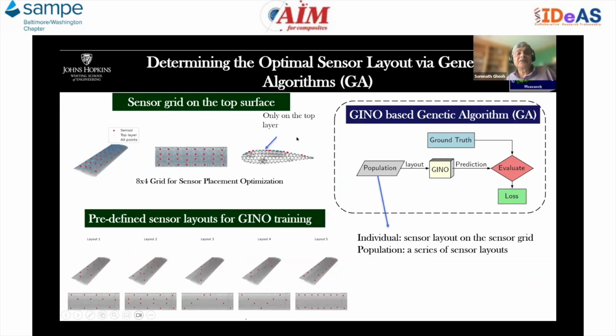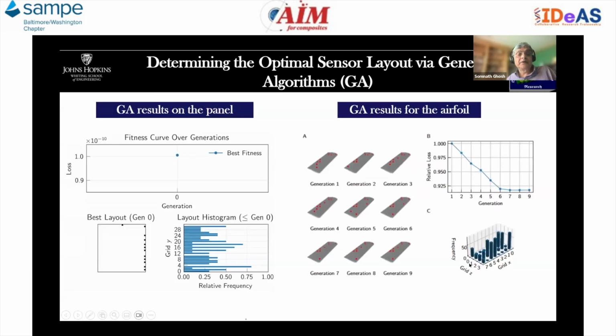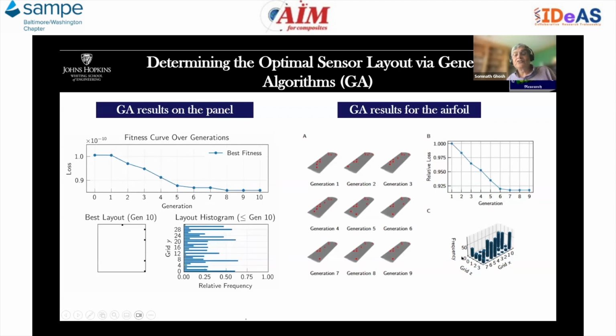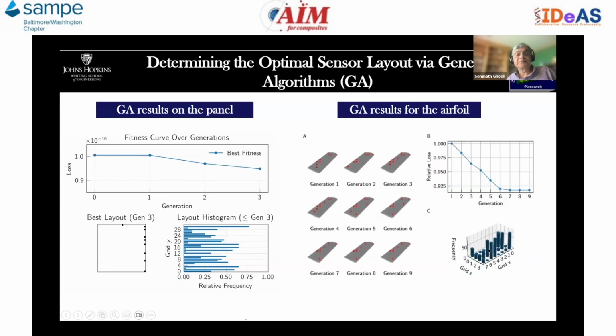The last thing here is we also have coupled this analysis with a genetic algorithm-based optimal sensor layout schema, where you can train this genetic algorithm using basically the placement. This is a sensor grid on the top surface, and these are some of the sensor layouts, and you can basically use this GA to come up with a loss function that corresponds to the difference between the ground truth and the predicted values corresponding to different sensor layouts to give the optimal behavior. So these are some of the sensor layouts for the panel, and this corresponds to some of the sensor layouts for the airfoil structure.